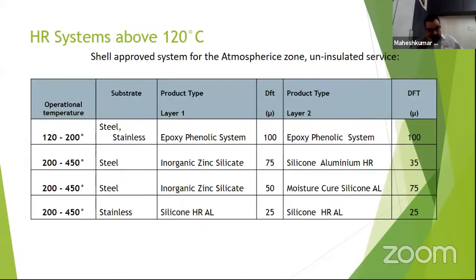But what happens? The systems which are above 120 degrees C, when we see areas like atmospheric zone, uninsulated services, they perform very well. Steel onto the stainless steel, onto the various requirements. DFT requirements in those systems could be from 25 microns to 100 microns. Now, these coatings give you certain properties, but they may not be used to protect the insulation or insulated pipelines or any type of insulated equipment.